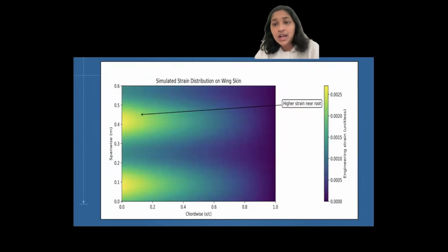This strain map shows how the wing bends under load. The brighter colors near the root are completely normal. That part of the wing always carries the most stress. The important part is the coloring stays smooth everywhere else. If my layers had caused any issues, you'd see sharp jumps or bright spots in random places. But because everything bends gradually, it tells me the layers bend along with the wing naturally. That matches the numerical result too. The total mass went up by only about 0.054%, which is so tiny that the structure basically behaves the same as before.